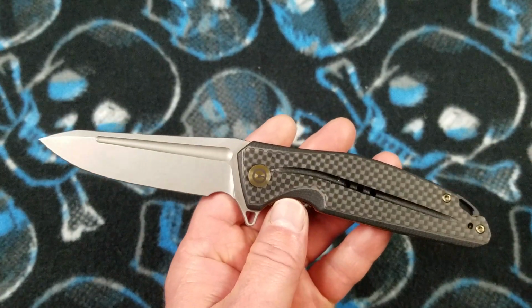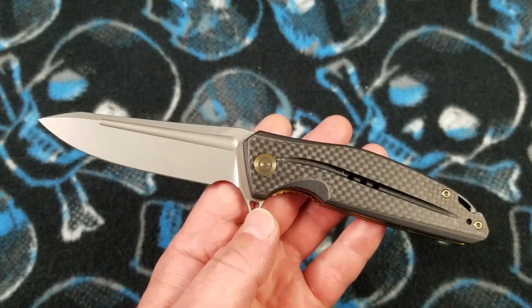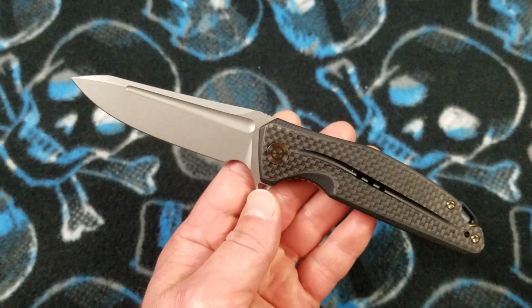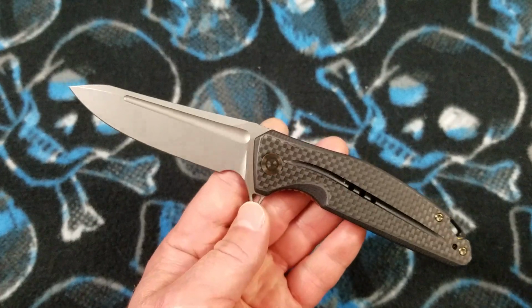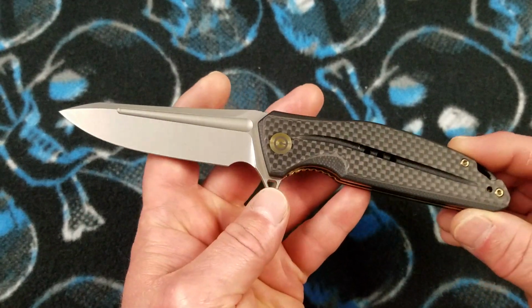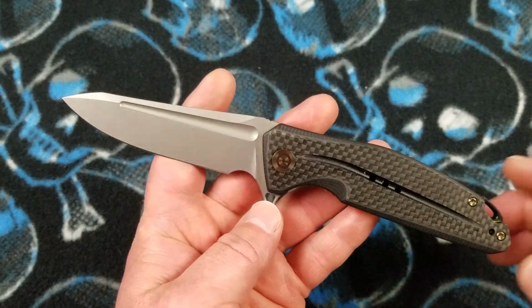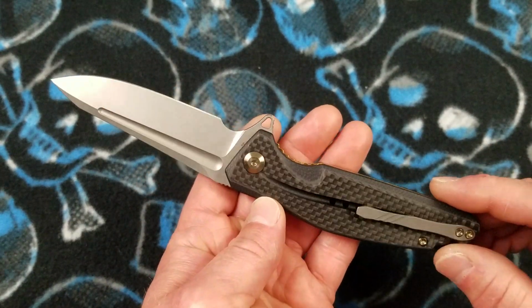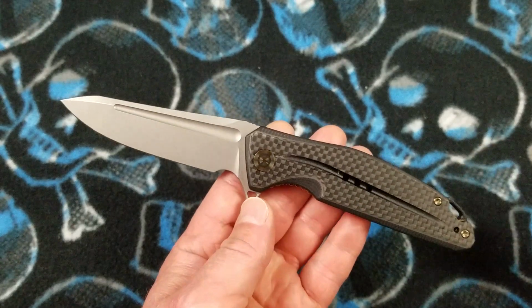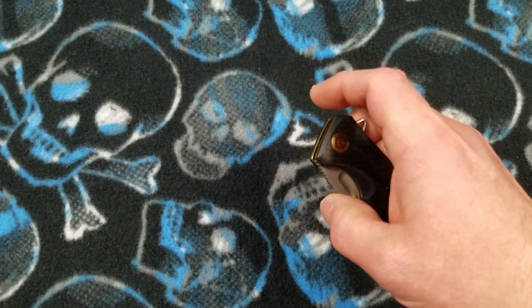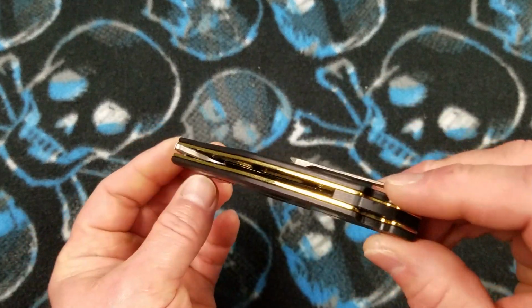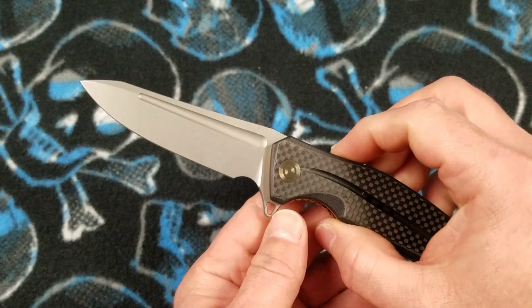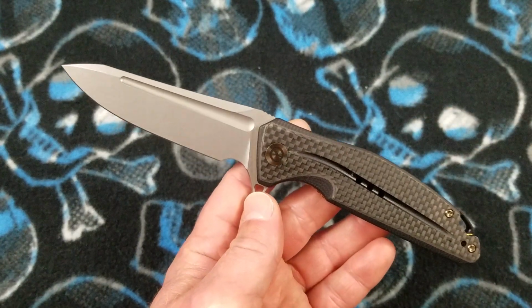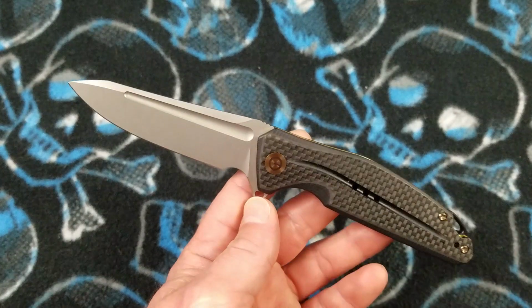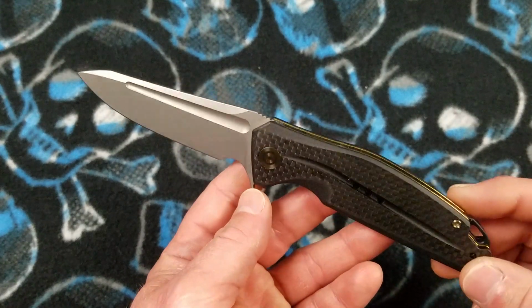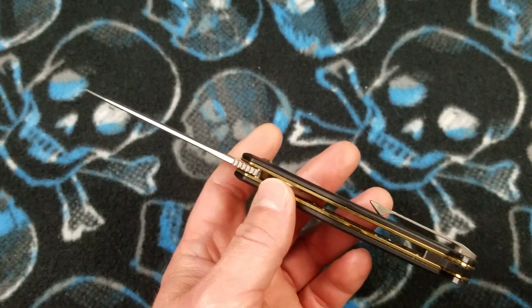Your handle to blade ratio was like 0.75, which is very good. And your weight, a very reasonable 3.74 ounces or 106 grams. Like I said, guys, this is on the upper medium end of an EDC knife with basically a 3.5 inch blade and an 8 inch overall length. But you're slightly above, but you're right at that 1 ounce per inch of blade length, weight to blade length ratio, which is very good. It's becoming more and more of a standard to judge, as far as that characteristic goes